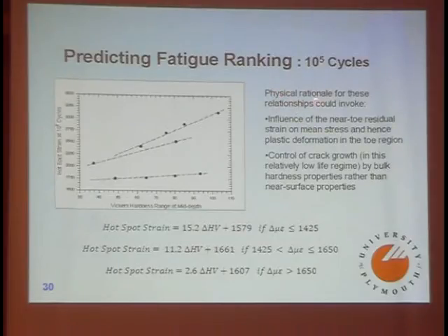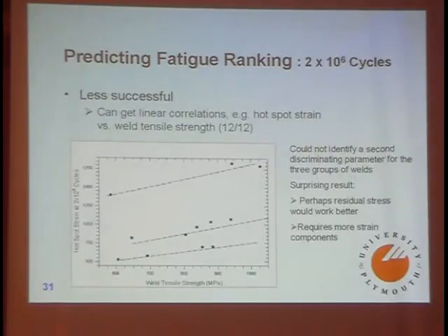So when you try and put a physical rationale for these relationships, you can't, with the data set we have, get a full rationale, but you can say, well, it seems reasonable that the influence of the near toe residual strain on mean stress, and hence plastic deformation of the weld toe, is important. But control of crack growth in this low life regime, where early crack growth is relatively limited as a percentage of fatigue life, could be by bulk hardness properties rather than near surface properties. And that's why you need the mid-depth hardness range as well. But that, I think, is reasonably successful.